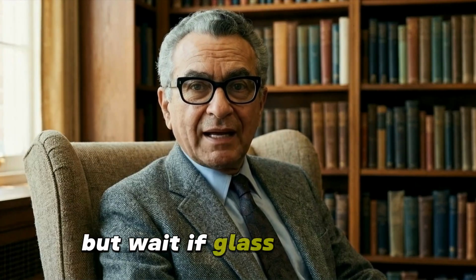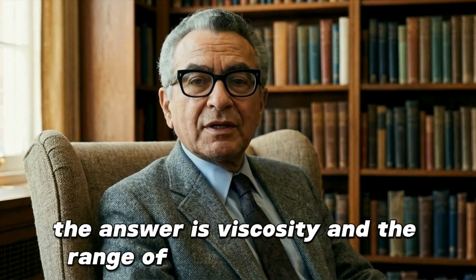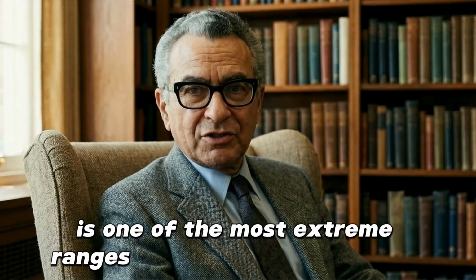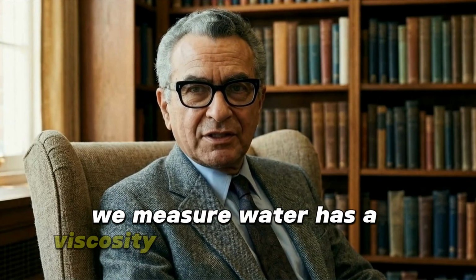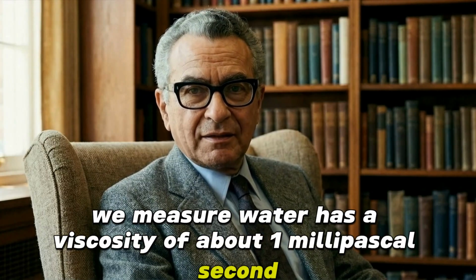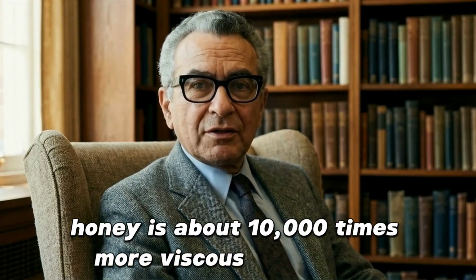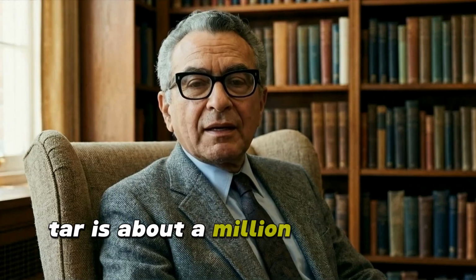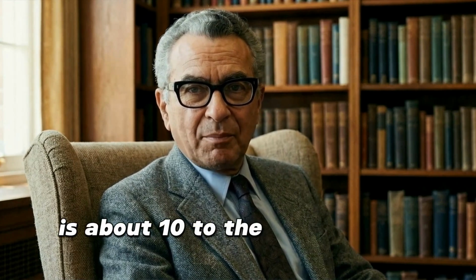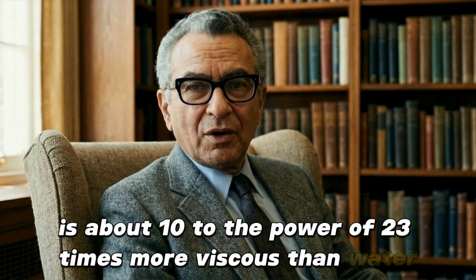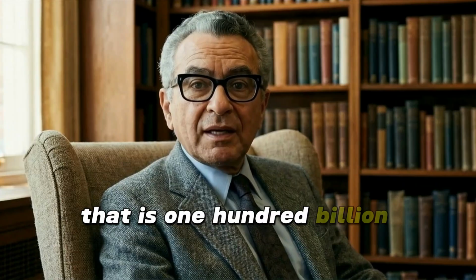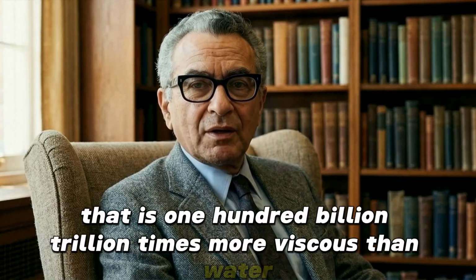But wait, if glass is a liquid, why does it not flow? Why can you lean on a window without it slowly oozing downward? The answer is viscosity, and the range of viscosities in nature is one of the most extreme ranges of any physical quantity we measure. Water has a viscosity of about 1 millipascal second. That is the unit. Honey is about 10,000 times more viscous than water. Tar is about 1,000,000 times more viscous than water. Glass at room temperature is about 10 to the power of 23 times more viscous than water. That is 100 billion trillion times more viscous than water.